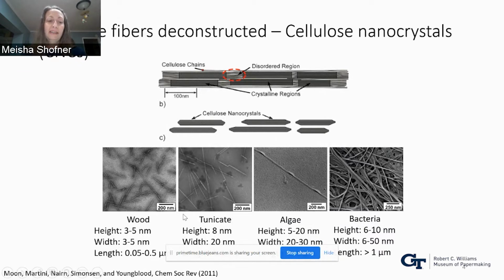If we look at these wood-based cellulose nanocrystals, we can see they are quite small. They have a roughly square cross-section, about 3 to 5 nanometers wide and 3 to 5 nanometers high. And then the length is on the order of about half a micron, or 500 nanometers. If we look at the other sources, tunicate, algae, bacteria, these can be much larger and longer. So the kind of nanocrystal we get depends on where we're sourcing it from.